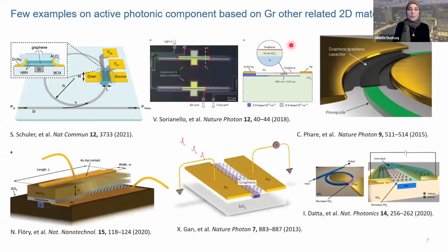So here are a few examples of how 2D materials have been implemented to functionalize photonic chips. Basically, we can see here a ring resonator, and they integrated a double split graphene photodetector, which is based on the photothermal effect. And here we have phase shifters and electro-absorption modulators. We can also have a heterostructure with other 2D materials to do much better photodetection with graphene. And also many other phase modulation, plasmonics, graphene modulators, and they are reaching something which has been achieved by three-dimensional semiconductors in terms of speed.